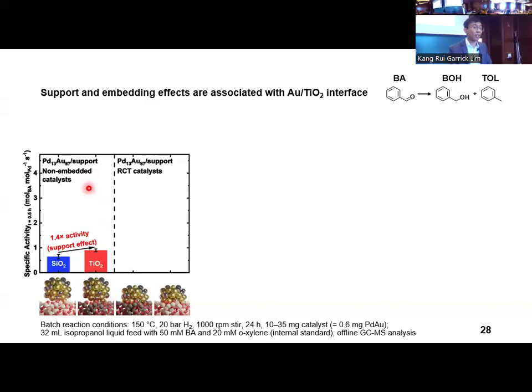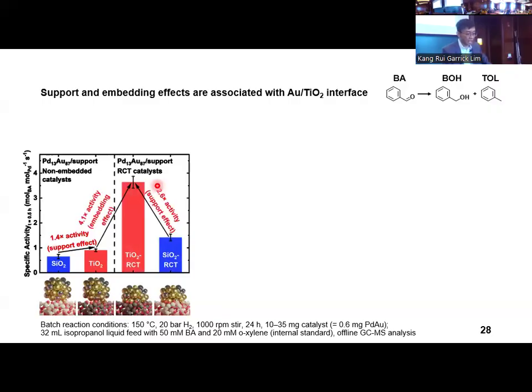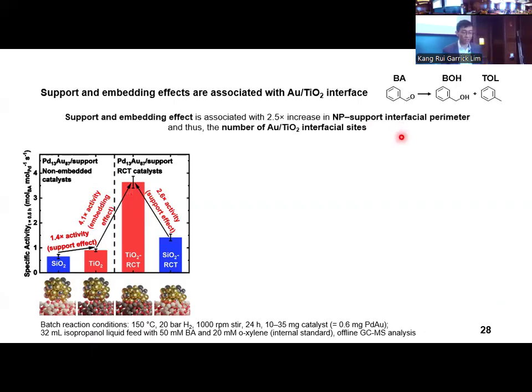Next, we compare the non-embedded to the partially embedded RCT catalyst to study the effects of nanoparticle embedding. Partial nanoparticle embedding enhances the activity of the titanium-supported catalyst by 4.1 folds, which was initially surprising to us, since the RCT catalyst exposed only about 15% of the nanoparticle surface area to reactants. This activity enhancement due to partial nanoparticle embedding, together with a stronger support effect in the RCT catalyst, is highly associated with an increase in the nanoparticle support interfacial perimeter, and thus the number of gold titanium interfacial sites.